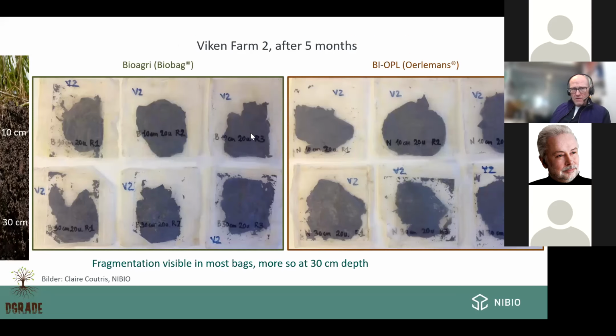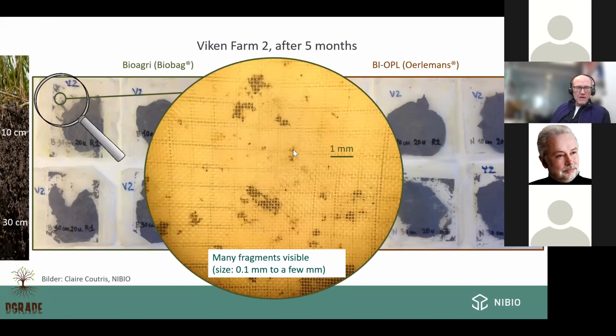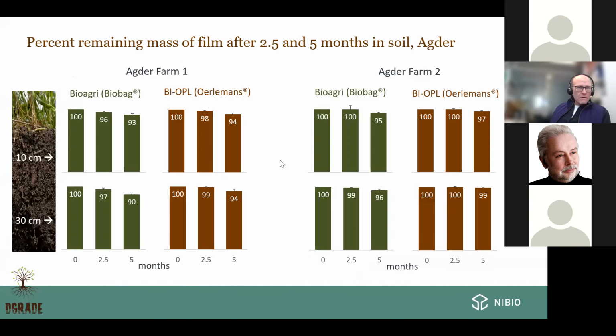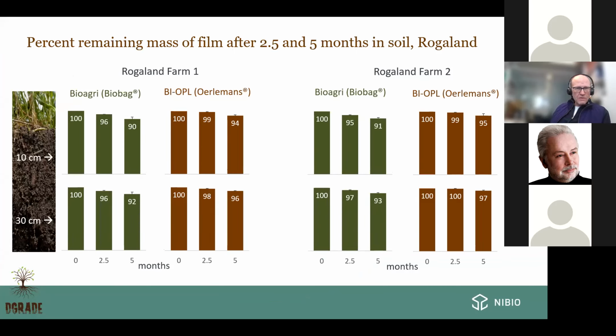The pouches, when we excavated them and cleaned them, we could clearly see that there were fragments inside the mesh bags, and we opened them and quantified this. Similar for the farm on the southeast coast of Norway, even less degradation compared to the farm close to Oslo. And finally, close to Stavanger, also degradation rates that resemble a bit what we saw in Viken, around a maximum of 10% after 5 months.